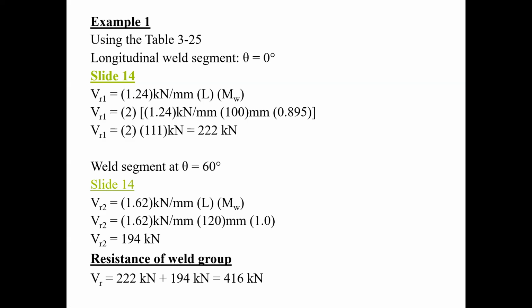Okay, so guys, I prefer using the tables. Like I said, if you don't check the base material, you can sometimes overlook the fact that the orientation of your weld can be stronger than the base material, and therefore you might have slightly overestimated the VR value. Whereas in the table here, it made sure that when you use this value, it was the base material that ended up giving you this value and not the value of the weld itself. And that's what I like. And now we got exactly the same value. I find that this is much easier. The only thing that you guys have to keep in mind is how to calculate that MW.